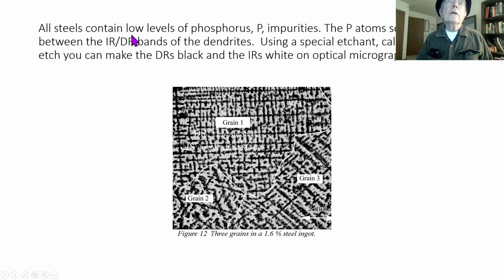All steels contain low levels of phosphorus. It is an impurity common in steels. The phosphorus atoms segregate between the IR and the DR bands of the dendrites. A guy called Stead, around 1902 or 3, discovered a special etchant. If you etch the steel, Stead's etch, the DRs turn black, IR is white in optical micrographs, and lo and behold, you can see the aligned dendrites beautifully, and you can see all the interdendritic regions